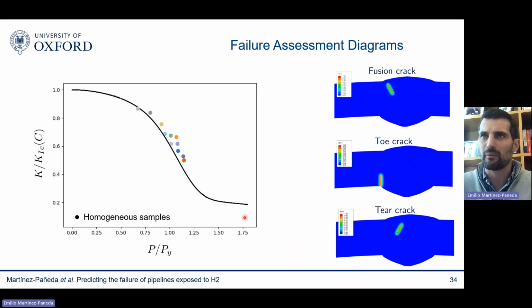And what this means when comparing to your finite element model is that on the x-axis you have the plastic collapse mechanism, so this is pressure versus yield pressure. On the y-axis you have the stress intensity factor versus the fracture toughness. And what industry is doing is trying to measure the toughness as precisely as possible and substituting it here. So this is what industry is going to use. And when you do a sophisticated model, then you can plot points in this failure assessment diagram. These are failure points, which means that if the point is in this area, your failure assessment diagram is not appropriate, because it told you the model shouldn't fail, but the model failed. So let's see how